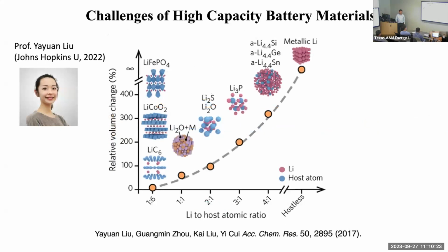So the challenge we are facing with the new materials: in this plot, the vertical axis is relative volume change versus the amount of lithium you store. This is the lithium versus the host atomic ratio. The higher the number, the more energy you are going to store. But the more lithium you're putting in, the relative volume change will go up tremendously. For traditional materials, the Nobel prize winning work, it's less than 10% volume change. But new materials coming in often show volume changes of a few 100%. So it's much more volume change right there.